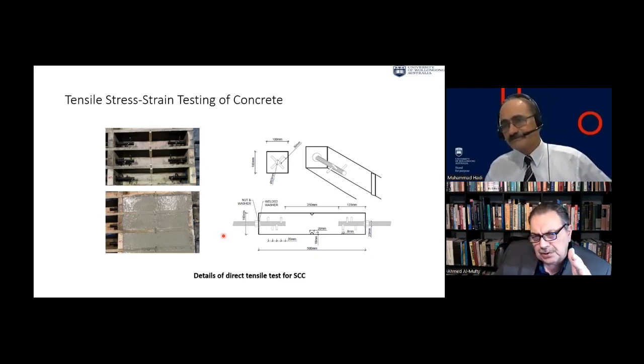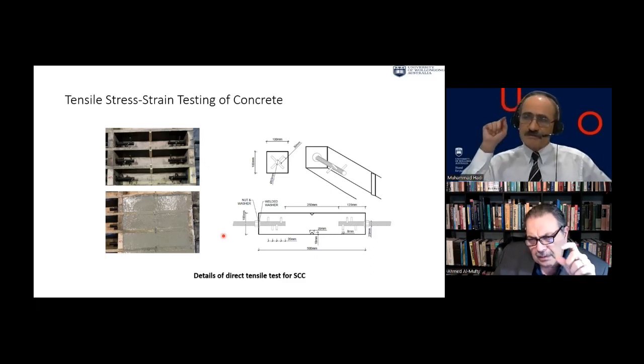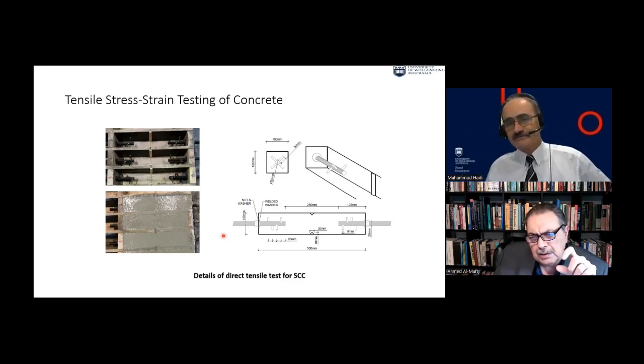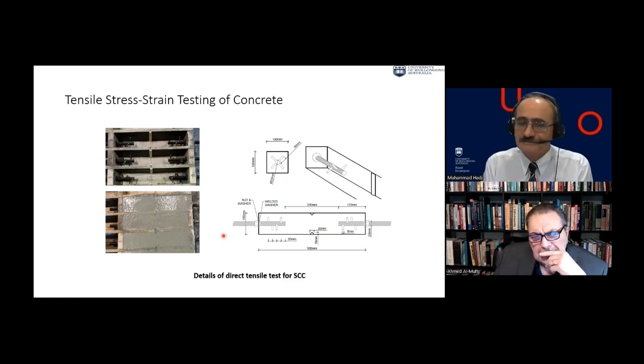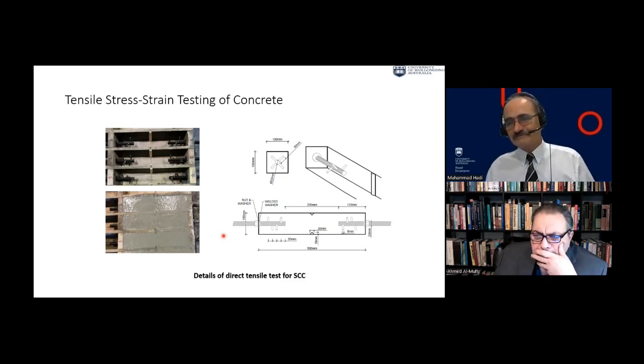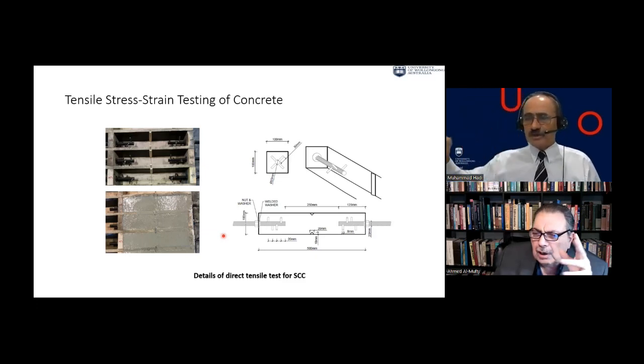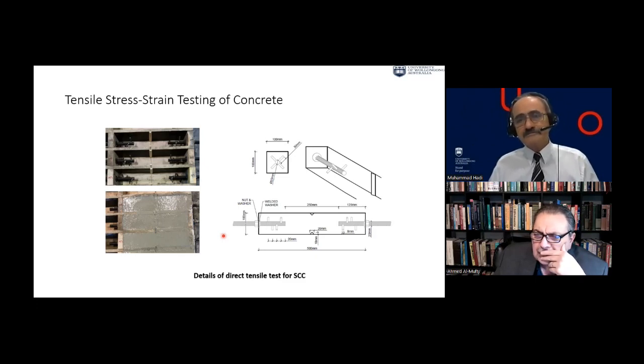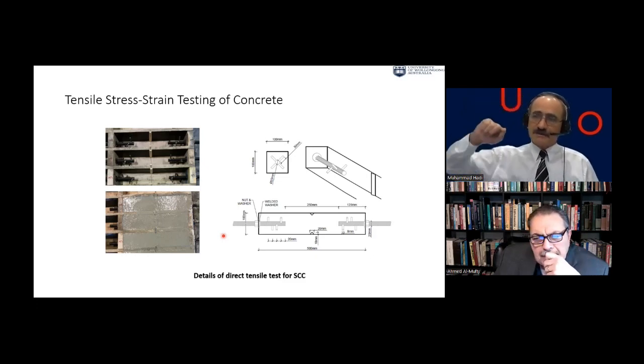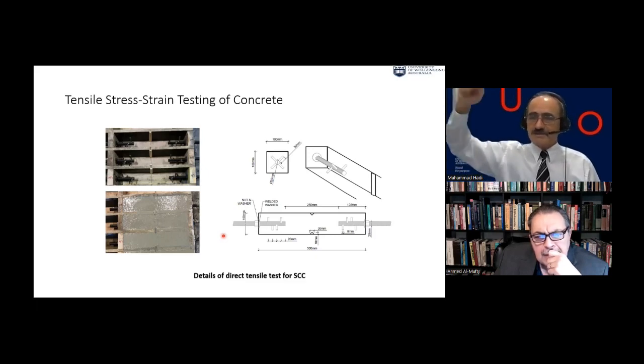Yes. But because of the notches, we are forcing them to break at that location. You're making it break in the middle. The area is smaller, yeah. That will cause the stress concentration to be there. And how much? Can we know? Less than 10%. How much is the tensile strength? About 10% of the compressive. So it's in the same trend, roughly. But we have all the stress-strain relationship in tension. We have the drawing.